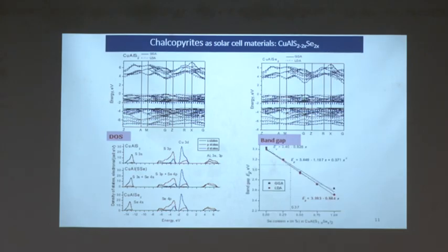You see, we have a formula. It was confirmed by experiment, but for example, when we need a band gap of 2.8, we need such a composition. And such calculations and measurements were done for many materials.